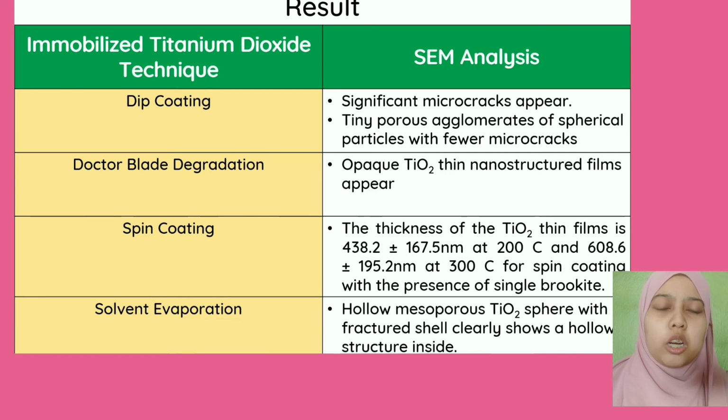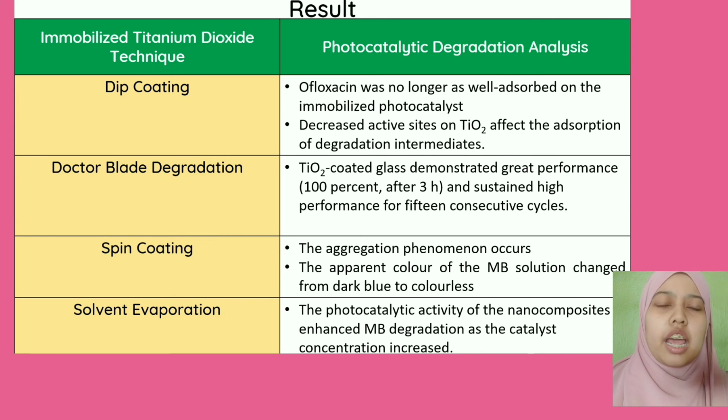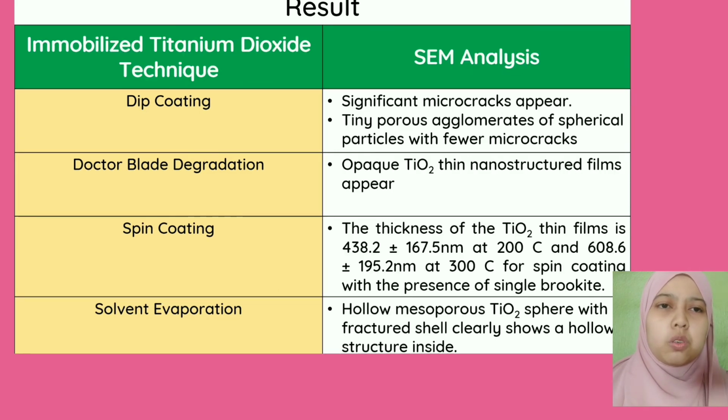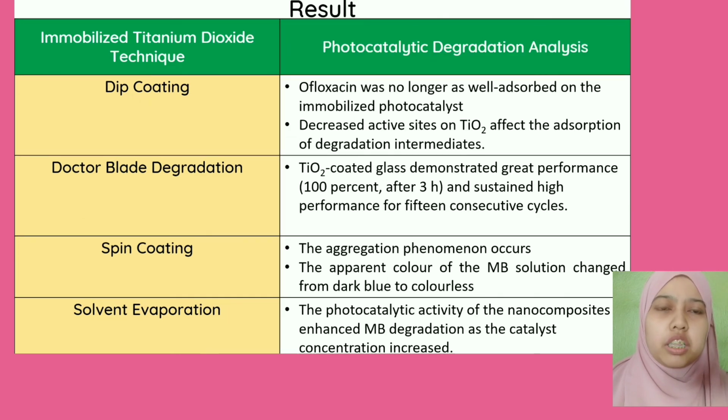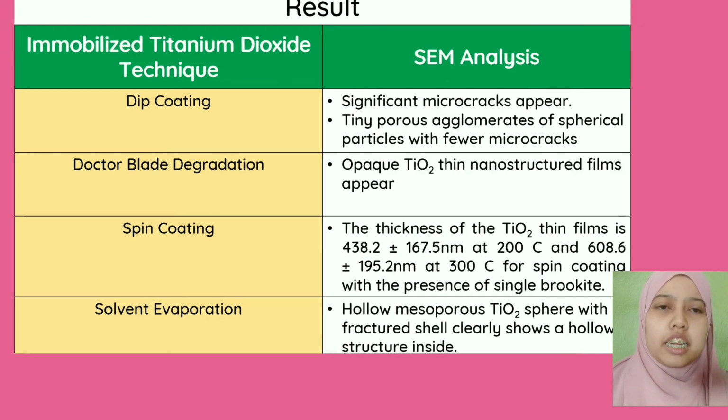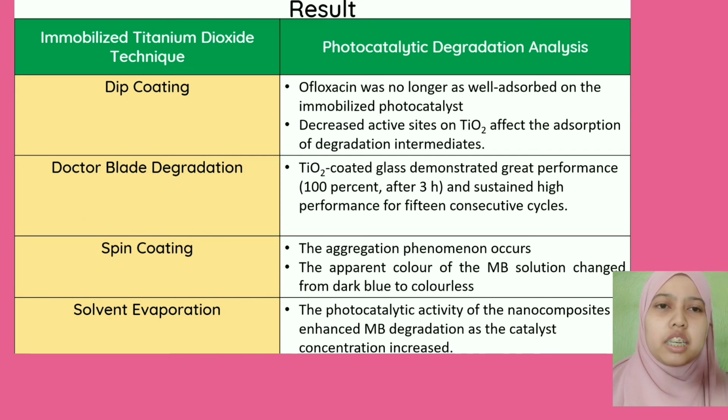These nanoparticles weakly bonded to the matrix are exposed to the solution and may be easily washed out during use. The loss of activity at higher concentrations of the photocatalyst suggests a higher detachment of the particles from the matrix.